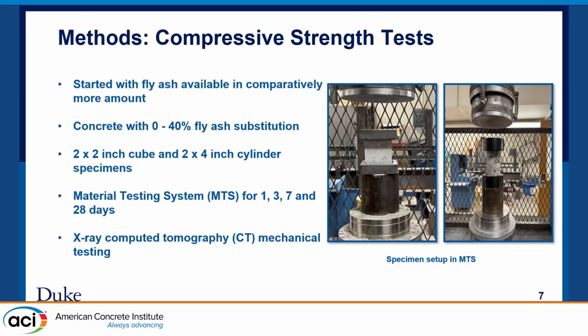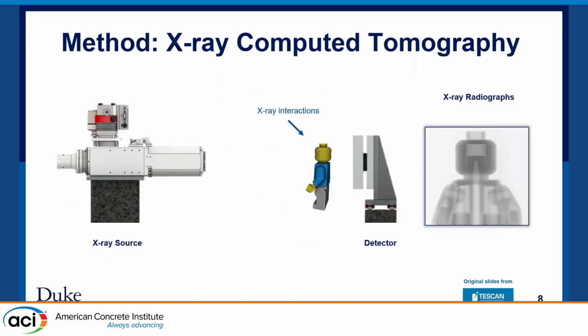For the compressive strength test, we started with the fly ash we had in comparatively more amount. We substituted 0 to 40% of those fly ashes in our samples and tested them at different days for the compressive strength of those samples. After this, we moved to the X-ray computed tomography mechanical testing of those samples. So what is X-ray computed tomography? X-ray computed tomography is the imaging technique used to create detailed images of the internal structure of the specimen that is being scanned.